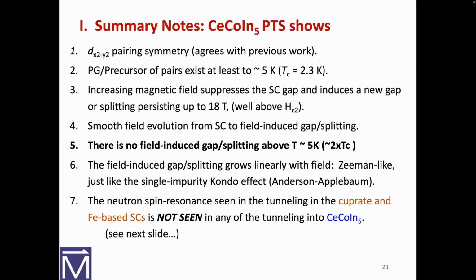So now I'm going to finish with a couple notes, and I'll finish early, yay. So we know that cerium cobalt indium 5 is dx squared minus y squared. We think that there's precursors up to about twice TC. Increasing the magnetic field does as we expect. It suppresses the superconducting gap, but then a whole other thing comes up and grows linearly with applied field. It's interesting that the evolution from above TC to this other thing is just very smooth. You see them both at the same time. I think that's a key. If you go above twice TC, you don't see this magnetic field effect. So there's something that you have to be near TC.